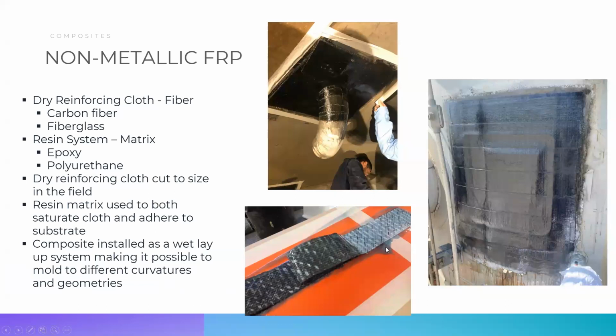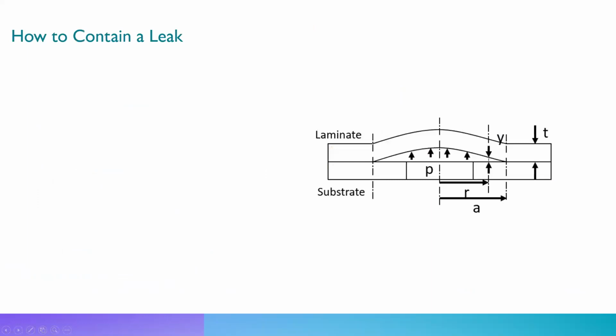It's laid up in the field wet, as you can see here. So this is the cloth, and the resin is being used to saturate it. And once you saturate the resin, you can wrap around a pipe, and then once it cures, it forms an outer pipe, basically an outer wall that reinforces the pipe wall and actually can contain leaks. So how do we use this system to contain leaks?